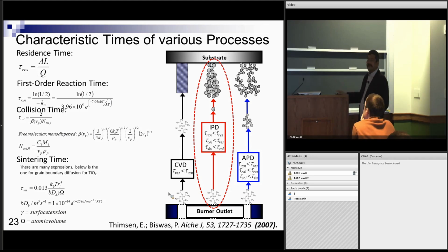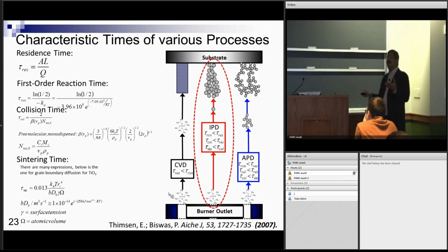So this is a chemical reaction, just simple chemical kinetics, which allows me to see the conversion and create the oxide. I'm bringing in an organometallic. I don't want to deposit that. I really want to deposit the oxide. So I want it to chemically react. Then there's a collision time. Once I react and form particles or nucleate them, I want them to collide, and there's a collision time, and then there's a sintering time. Okay, so a balance of all of this and controlling it, and I can control it by controlling the flow